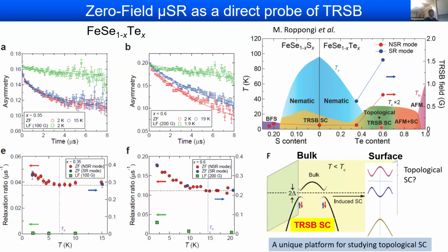I see. But so there's really no ferromagnetic impurity. I mean, it's known that you potentially have excess iron and things like that. There's no such thing in this regime of the phase diagram? Right. So we carefully prepared the samples, and actually, if you go to this side, 0.8, we start to see the effect of the excess iron. It's a short range thing, but which can be checked by the difference between this zero field and the longitudinal field.